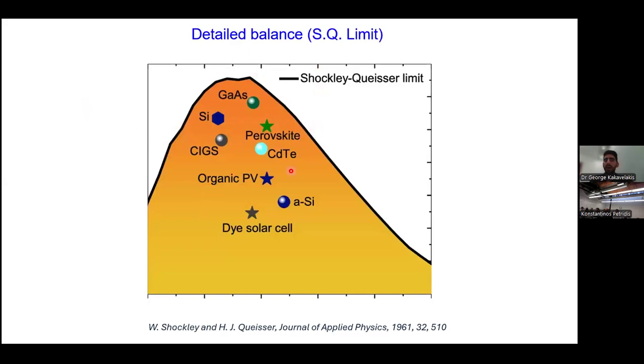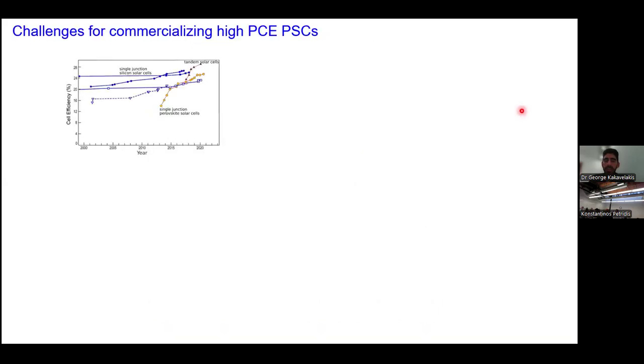Okay, and this is finally the efficiency map that we have. And of course, you saw that we didn't discuss this material that depicts the highest efficiency, because these types of materials are very expensive and they are used only for space applications, because they cost like 10,000 US dollars per square meter. They are extremely expensive and they cannot be used for commercial use. But you see nowadays that perovskite and silicon practically have the same efficiency.